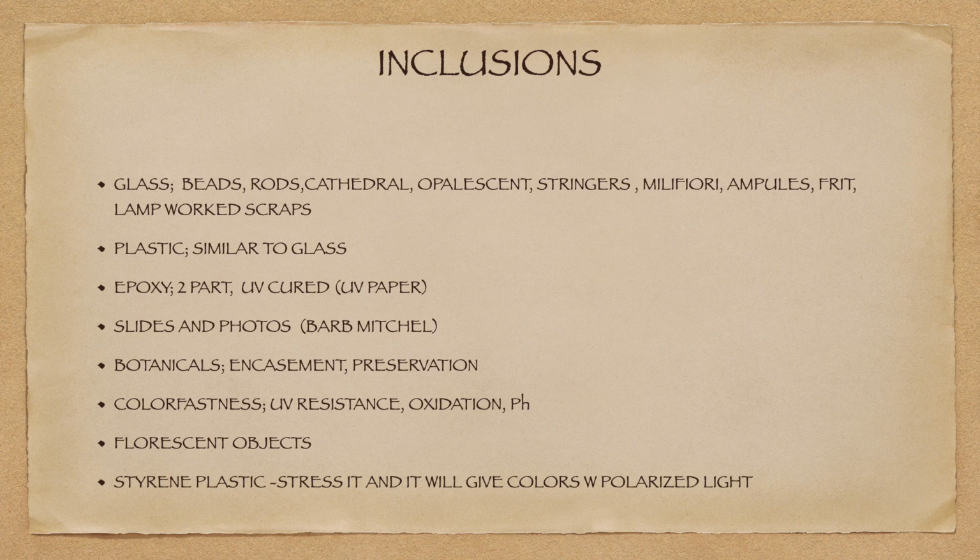When you're making a choice about glass, if the light source is coming through the end of the kaleidoscope and not from the sides, then translucent or transparent glass, like cathedral colored glass, is perhaps a better choice than opalescent, which tends to be opaque. Opalescent works better with the light coming in from the sides or from the front, from where the observer is situated.